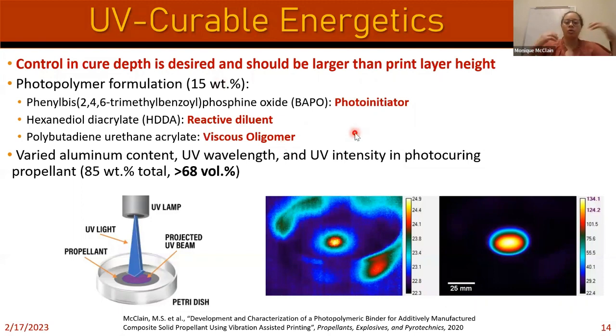But in general, we were able to make this mixture by heating it and sonicating the parts together so we could do some tests in the study. First we looked at the photopolymer and then we added that to our mixture. We varied the aluminum content, from 0% aluminum all the way to 20% aluminum. We tried 2 different wavelengths and some different UV intensities. But in general, the setup was relatively simple.